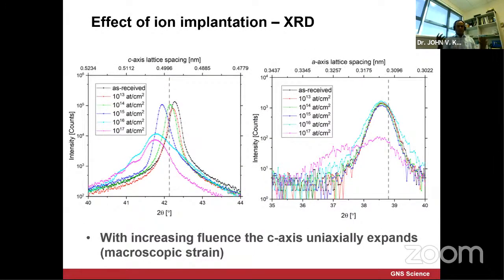Then obviously we all do XRD. So we looked at the X-ray diffraction and tilt angle perspective. If you look at the left-hand side, the dashed line corresponds to unstrained aluminum nitride, and the black line corresponds to as-received. But you can see as we start to implant zirconium, in this case at very low dose, 10^13 atoms per square centimeter, you're talking about sub-ppm. Then we are moving towards the ppm, and you're starting to see the strain.